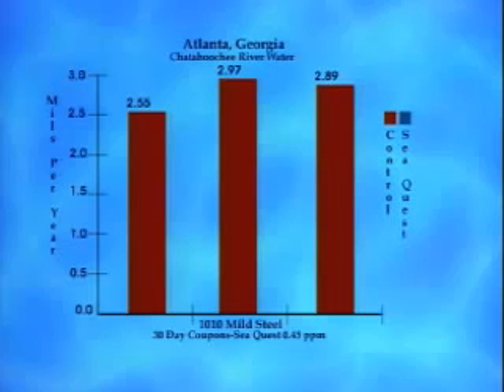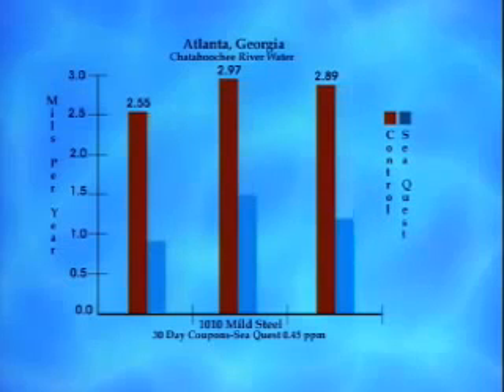These coupons came from the City of Atlanta corrosion coupon test, where Seaquest reduced the corrosion rates from an average of 2.8 mils per year to an average of 1.23, a reduction of 56% in corrosion rates. The control was zinc orthophosphate and pH control of 7.4, and the Seaquest treated coupons were running at a pH of 6.3.